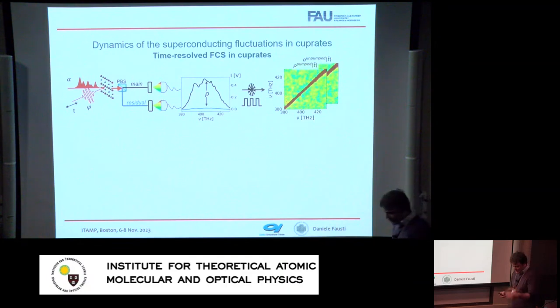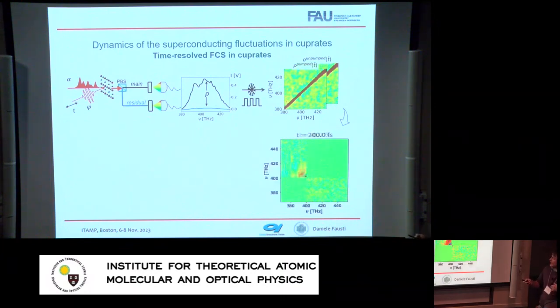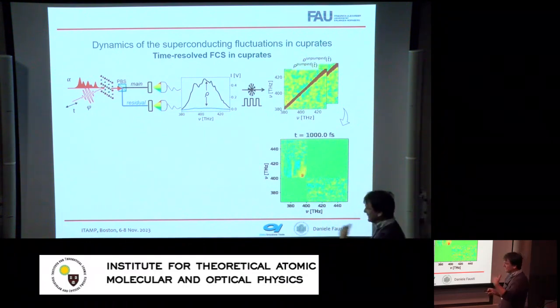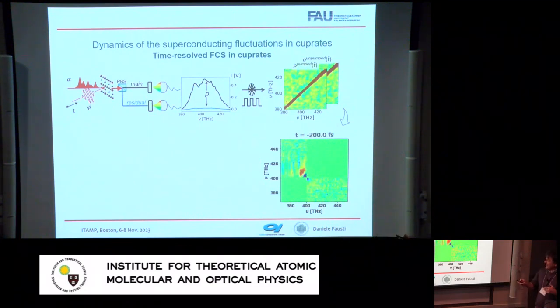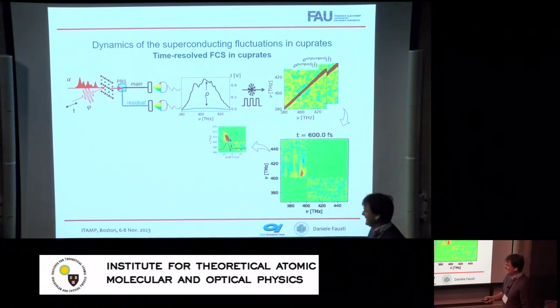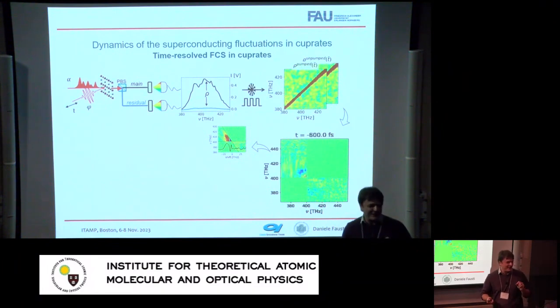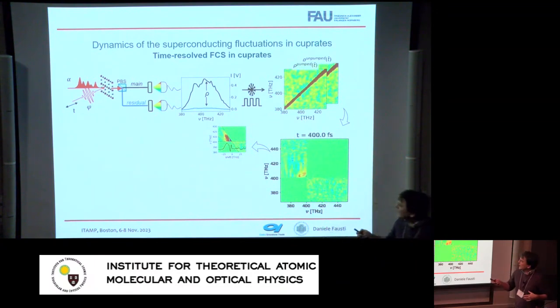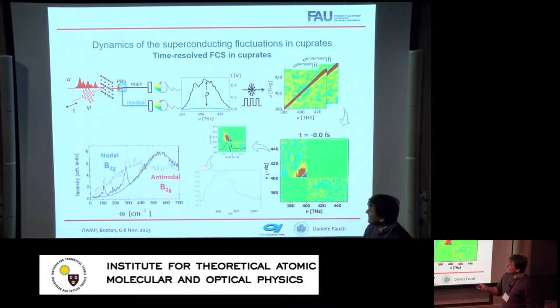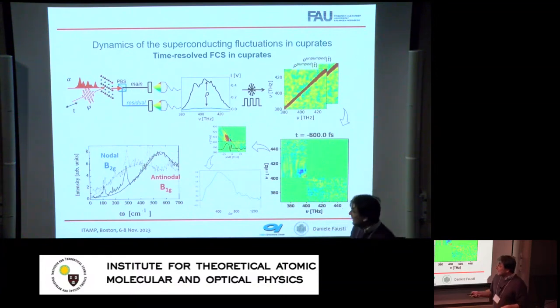And it took us a while to get convinced that what we are doing makes sense, but we started first on simple systems. And the idea is that we measure as a function of pump and probe delay. Now we can perturb the sample and quench the superconducting state, and we try to measure the correlations as a function of time. Now that I know how to analyze, after I spent 3 years on simple systems where the phonons are very narrow, I know that the only relevant quantity is the distance from the diagonal. I can actually confidently measure this quantity, and I can compare it with the Raman scattering, and essentially I realize that in the superconducting state of the cuprate, if I interrogate the system with these very wobbly pulses, I introduce spectral correlations which are in frequency very similar to the spectral correlation I get by Raman spectroscopy in the superconducting state.